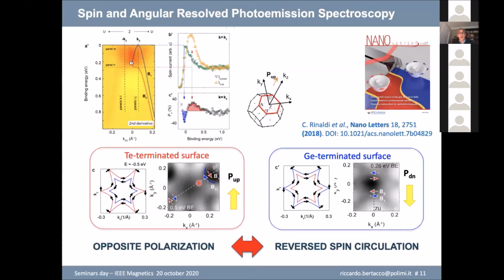So the idea here is that you can now control the spin texture by playing with the ferroelectric polarization. But at this point, we were facing a problem: we can prepare different surfaces in a pristine state, but how can we write a different state in a real device? With a PFM, you can write domains. This was demonstrated, but this is not a real device.